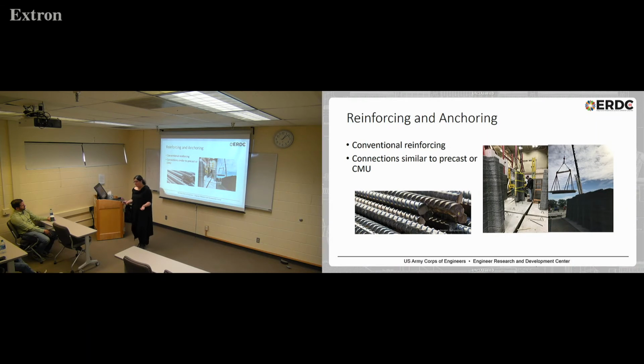It's very similar to using precast or CMU block type construction. So basically you can leave a cavity. If you're, say, printing a building, you can leave a gap in your wall that you can put vertical reinforcement into and then backfill that with concrete and basically use it as formwork that you never have to remove and actually add structural characteristics to your wall.